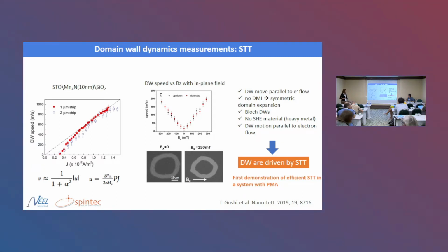And this completely excluded the presence of DMI, although we didn't necessarily expect DMI in this system because of the absence of heavy metal. So we concluded that domain walls are not driven by spin-orbit torque in this system. As I say, there is no spin Hall effect material. So we expect the domain walls to move in the direction of the electron flow. So the conclusion was the domain walls are driven by spin-transfer torque, and this is the first demonstration of efficient spin-transfer torque in a system with perpendicular magnetic anisotropy.